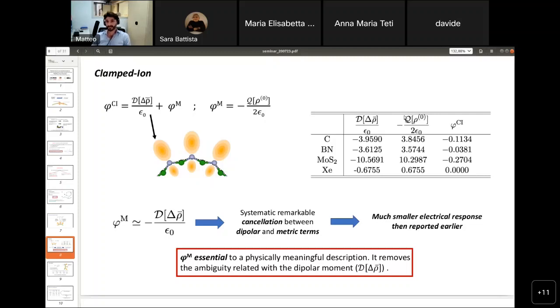But if you look just at the dipolar moment, we find that this is non-zero, and it is actually related to the ambiguities that I mentioned before. But when we sum the metric term, we find that the total Clamped-ion response is zero. So in such a case the response is zero, as it should be and as we expect. So the metric term is very important to remove the ambiguities coming from the consideration of only the dipolar moment, and to provide a physical result.